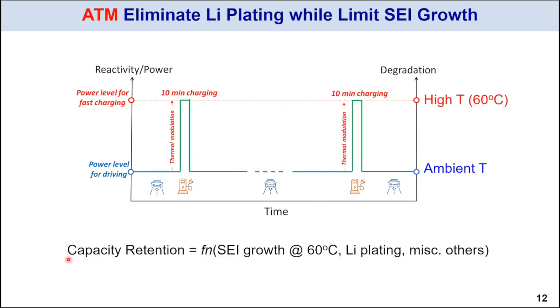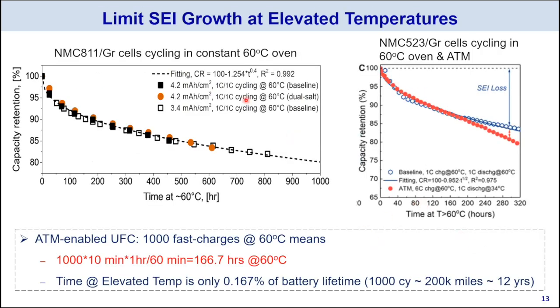So at the end, in this ATM mode, the battery capacity retention is a function of SEI growth at 60 degrees Celsius, and the degree of lithium plating, whether we can reduce or eliminate it, as well as some other miscellaneous factors, which all remain the same as in other normal conditions. Now, how do we limit SEI growth at elevated temperature? We did a lot of characterizations for a large number of materials.